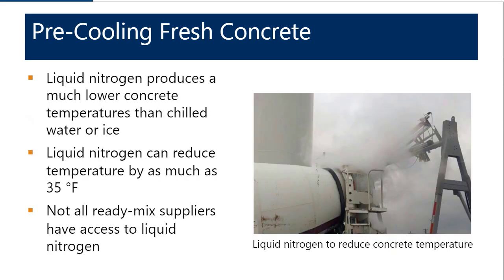One of the more efficient ways, and this is sort of the sledgehammer approach to pre-cooling fresh concrete, is the use of liquid nitrogen. Liquid nitrogen is very efficient at producing lower concrete placement temperatures, and it can do a much better job than chilled water or ice. One of the challenges with this particular approach is not all ready mix suppliers have access to liquid nitrogen. In some markets, there aren't any ready mix suppliers that have access to liquid nitrogen.